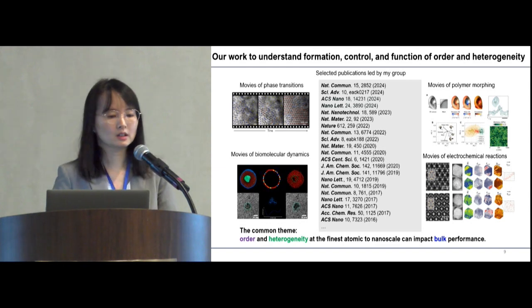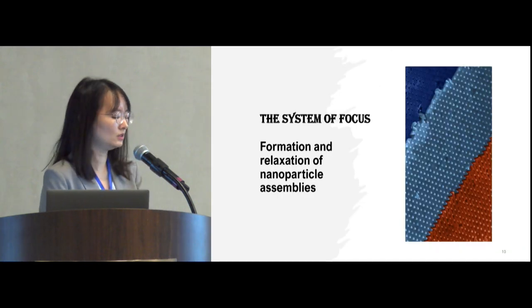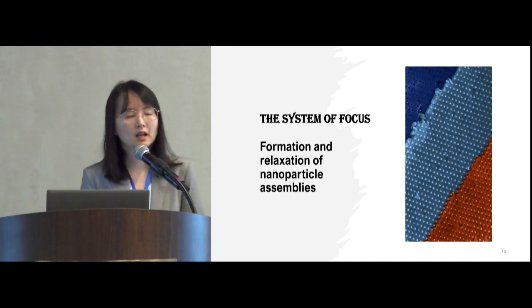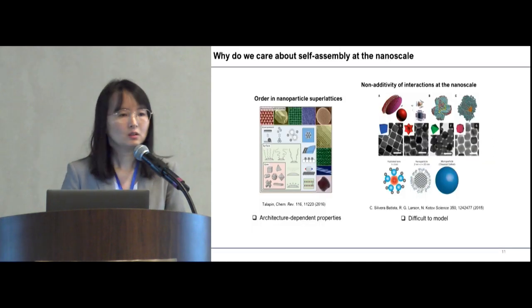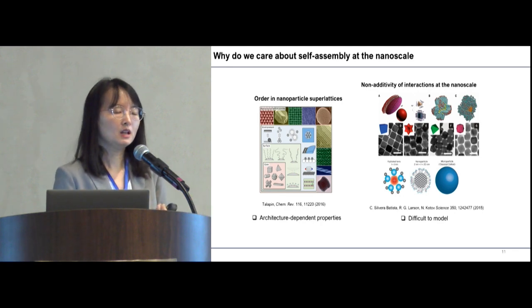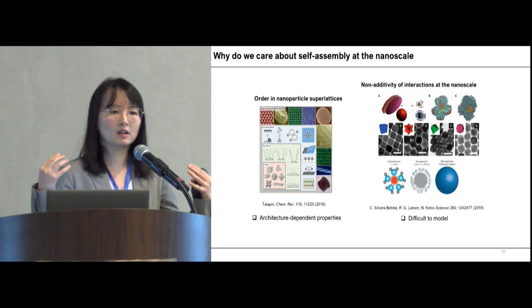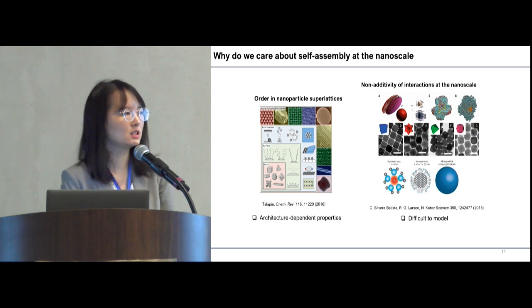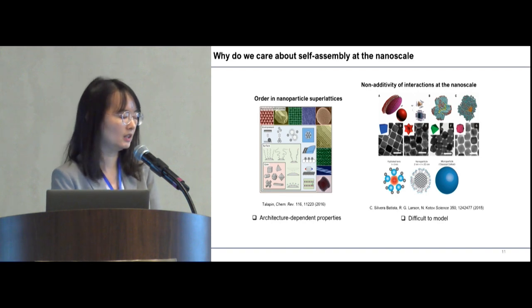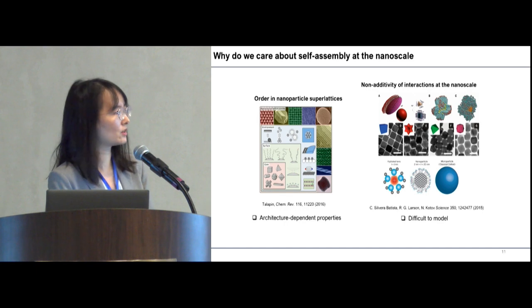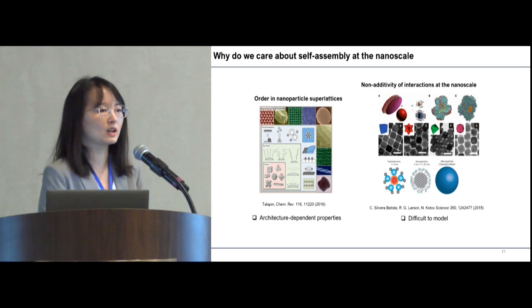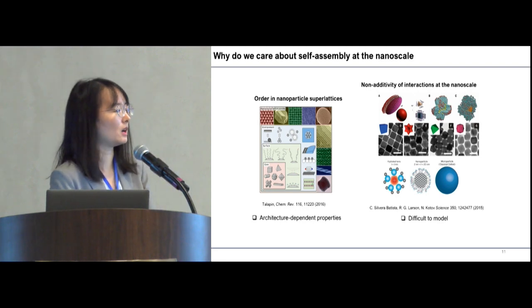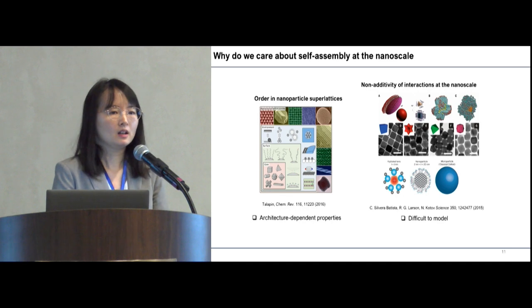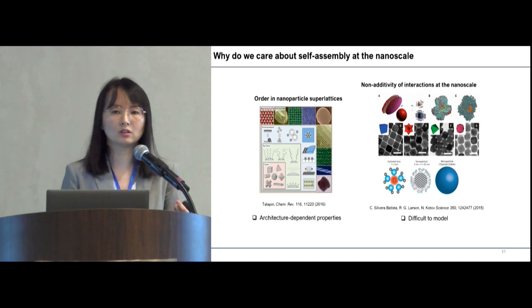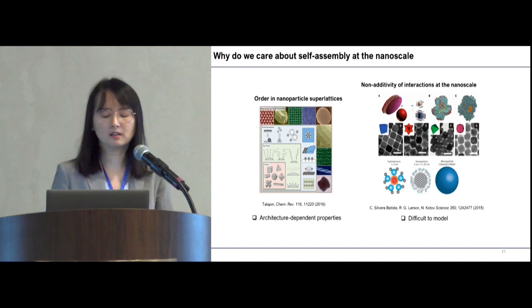For today's talk, I'm going to focus on the first type of movies. In particular, we're going to look into how the formation and relaxation of nanoparticle self-assemblies happen. So why do we care about nanoparticle self-assemblies? I already mentioned individual nanoparticles have interesting properties, but when they're put together through self-assembly, they start to have crosstalk, and that crosstalk can lead to collective properties that are sensitively dependent on the structure. However, for a long time, what people know about that structure is literally the single snapshots of the final structure. We do not really know the self-assembly pathway, and we cannot really engineer them efficiently. In the meantime, modeling this process has been difficult because the colloidal interaction at the nanoscale has been non-additive.